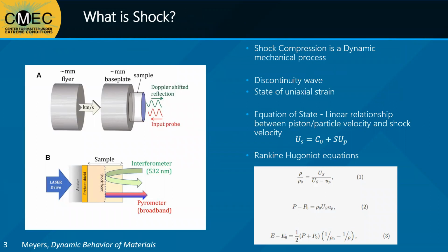So the direction of my research is to understand the behavior of these materials when under shock compression. Shock compression is a dynamic mechanical process defined as a large amplitude wave across which there is a discontinuity in the pressure, density, particle velocity, temperature, and other properties before and after the wave. Common setups for producing shock waves include gas guns, where a flyer disk is accelerated to several kilometers per second, or laser ablation, where laser energy is delivered to an ablator, causing it to heat up to millions of degrees and hundreds of millions of atmospheres of pressure.